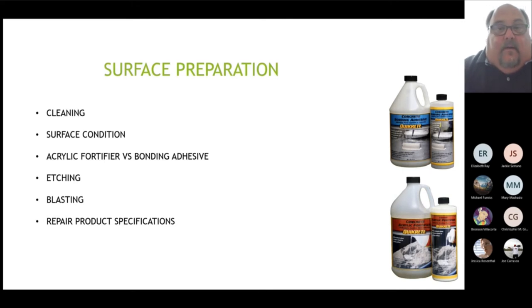Cleaning is really important to get as much grease as you can out. Dirt, paint, anything that's not concrete, not cementitious base, is going to affect how it bonds. And if it can't absorb, and it's always got to have some type of absorption rate into the substrate, it's going to float on top and it's guaranteed it's going to crack.